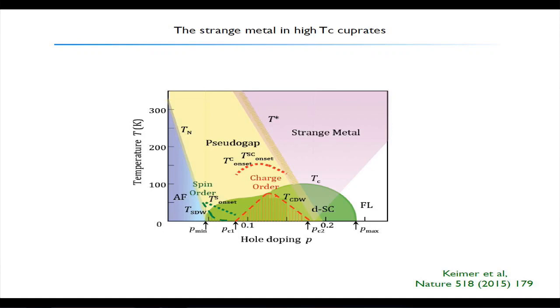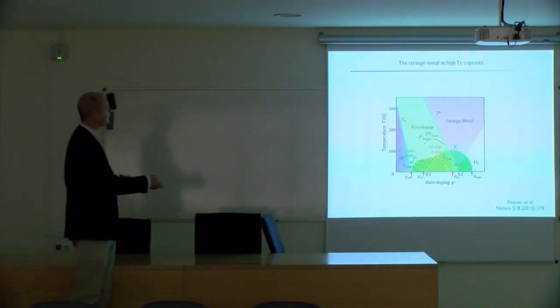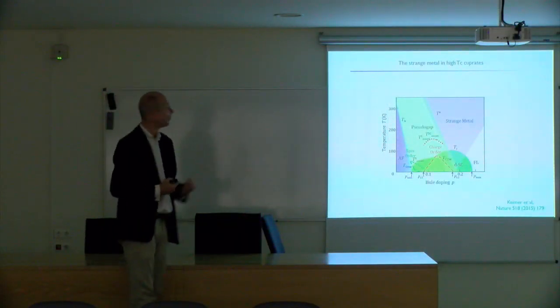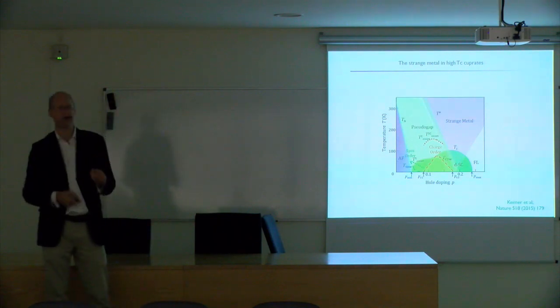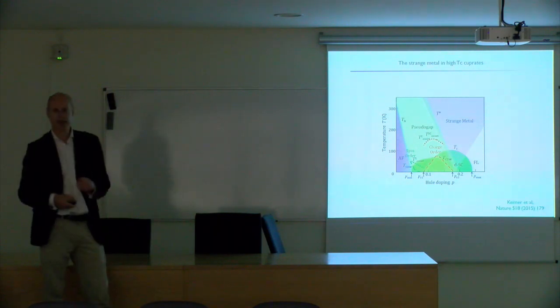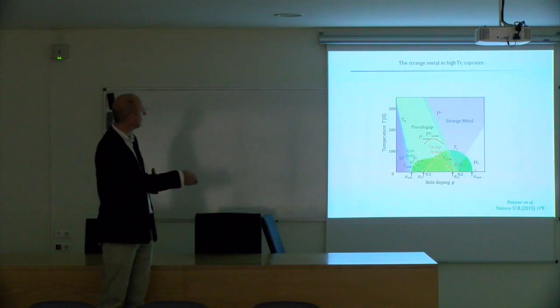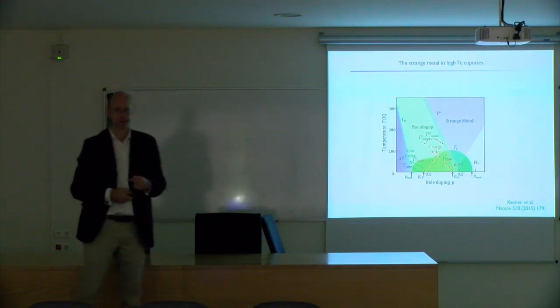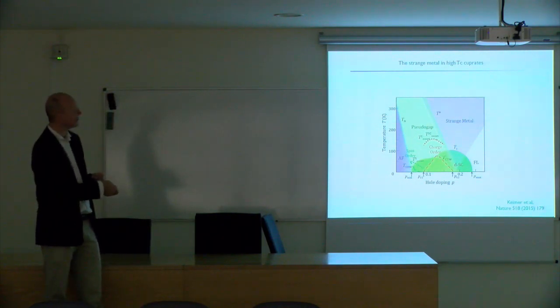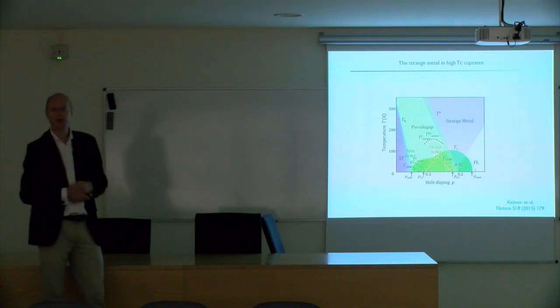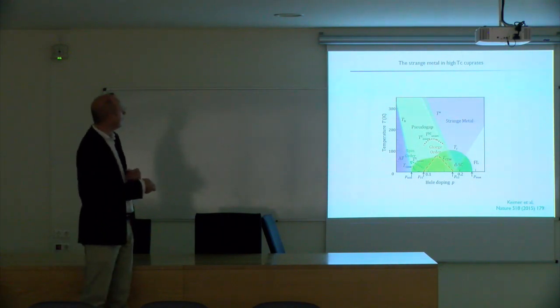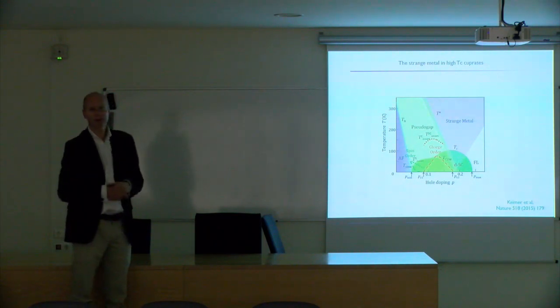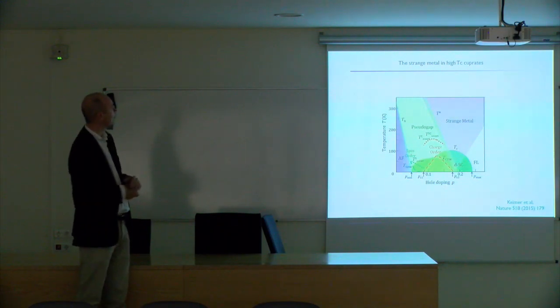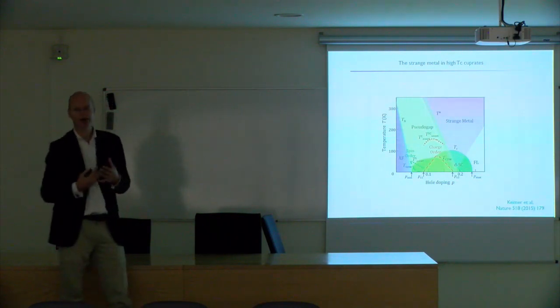Here is a phase diagram of these materials, where you have the temperature here, and this is the hole doping, right? So you replace one of the building chemical materials by an object which has fewer electrons in the system, then you get a hole-doped system. And if you dope to roughly about 20%, these materials show superconductivity at the order of 100 Kelvin.